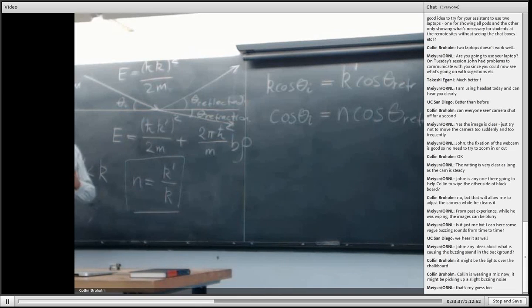So we will have the phenomenon of total reflection, but in this case it's total external reflection. So it's when I come from the vacuum to the dense medium with neutrons that I tend to have total reflection. Whereas in the case of optics, it's the reverse. You always have to come from the dense medium into the vacuum in order to have total internal reflection. So we have the opposite with neutrons, and that turns out to be really, really useful. I'll tell you a few words about that.